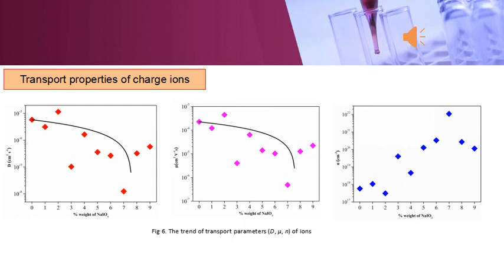So, figure 6 shows the trend of transport parameters of ions. From the result, it can be observed that the diffusion coefficient and the mobility of charged ions followed the conductivity trend, while the number or concentration of the charged ions shows the opposite trend. This is because a higher rate of diffusion and mobility of charged ions in the SPE can influence the increase of conductivity. This statement is based on Chu et al. 2015. And from the literature before this, it may be concluded that the movement of ions is also influenced by the addition of salt.